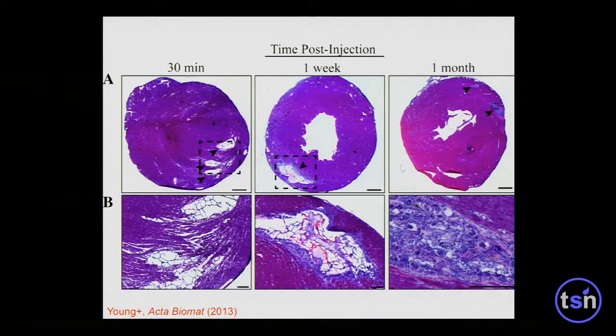And just as one last point, it's very imperative that you consider the translatability of these materials, and everything that I've told you today with dynamic environments would really have trouble being translated in vivo. This is just one example that I want to close with. This is our original material of thiolated HA, and this was actually work with Karen. Everything that we had done subcutaneously would have suggested that this material was biocompatible, but we found huge granulomas that resulted once we injected this material into SD rats and waited a month.